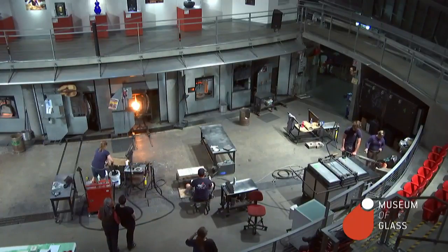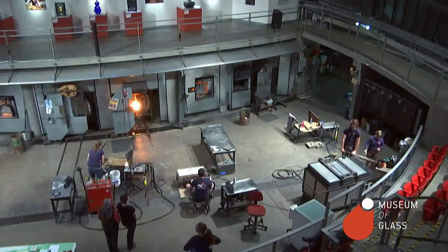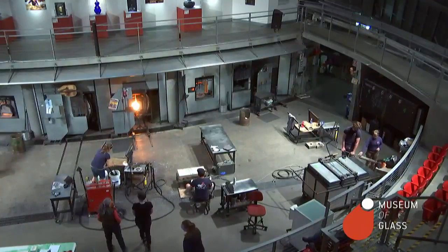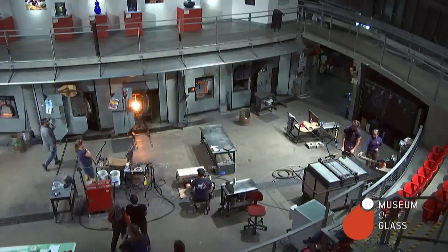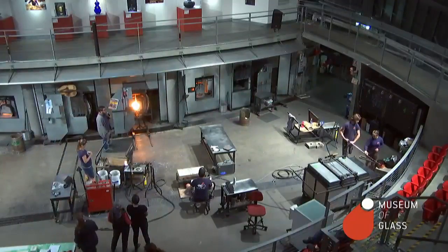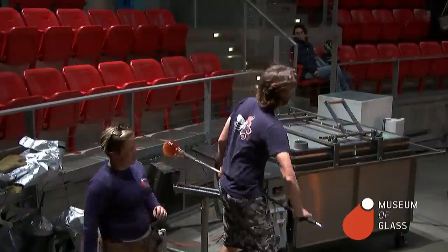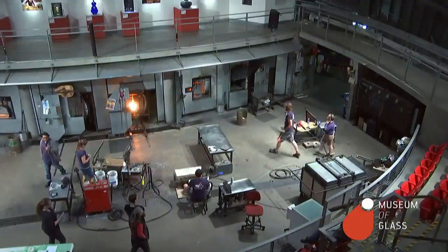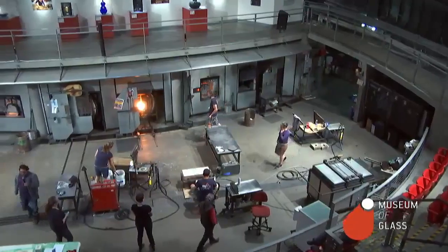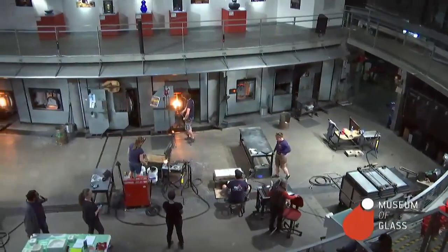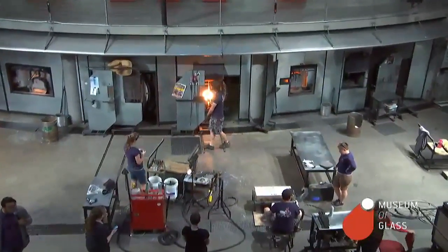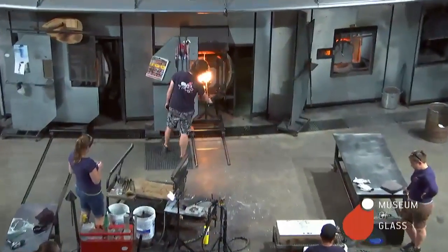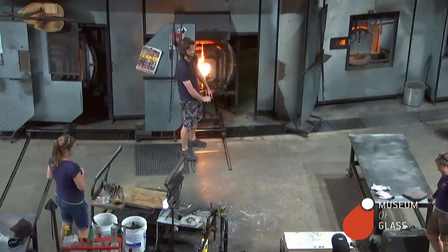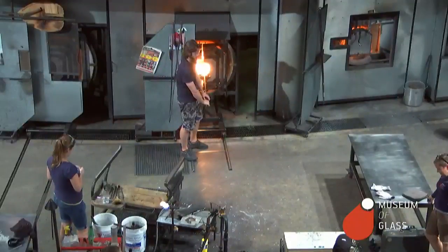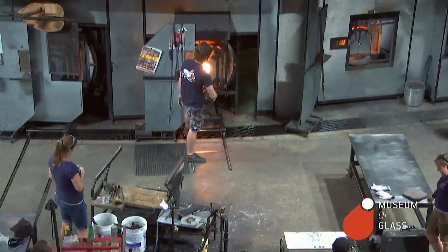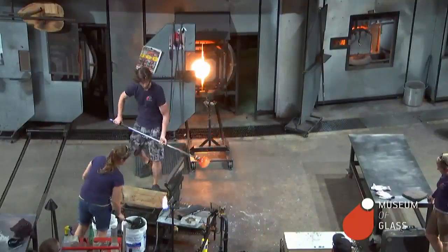Although these rods are specifically made for us, again, made out of that stainless steel, they still take a toll. Down here, we are using a pipe cooler, which is just some cold water that we run on the surface of the rod, and in turn, it cools down that rod, making it easier for us to handle. Notice that the shininess begins to leave the rod, especially towards the tip of the material. It goes from stainless steel to eventually that dull black. That deteriorated part, that's what that heat does to the material.